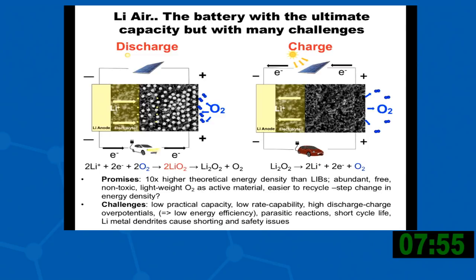In practice, the overall practical energy densities or capacities are low because you get pore clogging, so the pores fill up with these big particles and you can't get the oxygens through. You have low rates because of the difficulties of getting the lithiums and the electrons to the peroxides on charge and getting enough oxygen into the systems on discharge. And then you get very large overpotentials because of the difficulties of doing these reactions, which results in very low energy density. Parasitic reactions, short life cycles, and also lithium metal dendrites that are implicit to lithium metal technology are a problem that still needs to be solved.